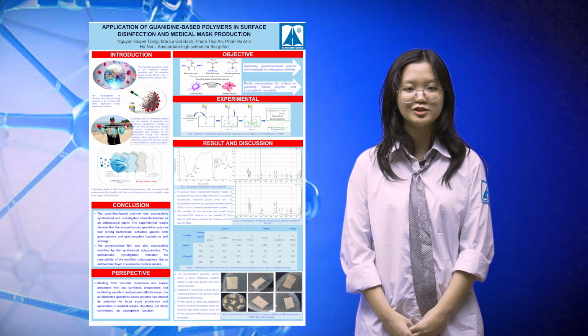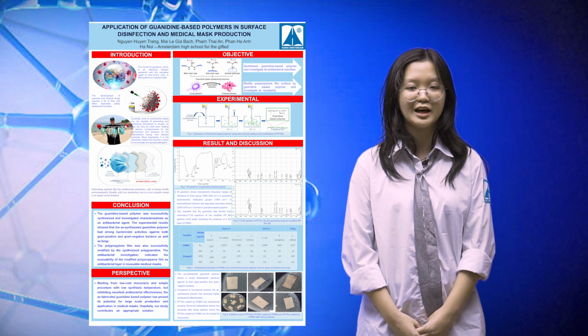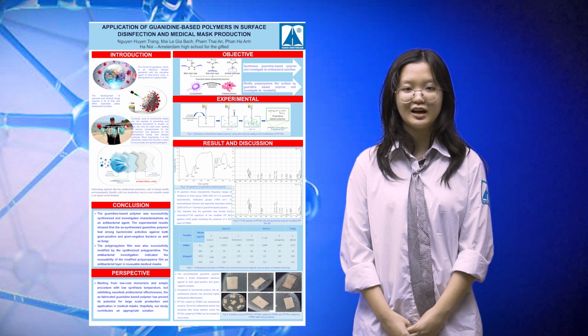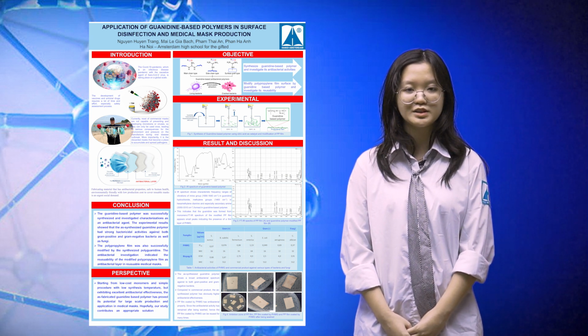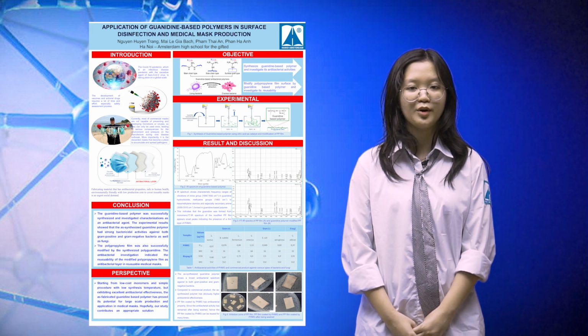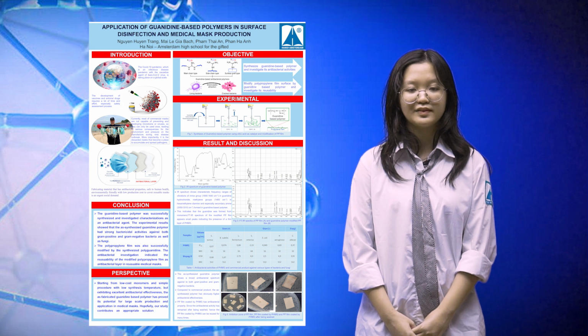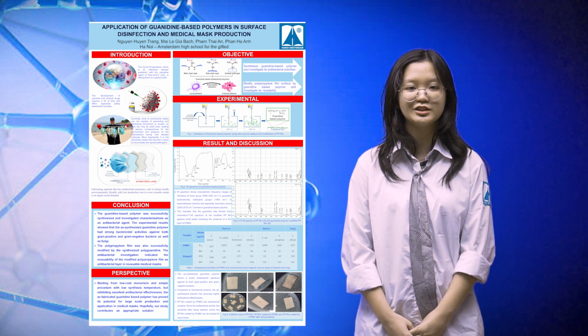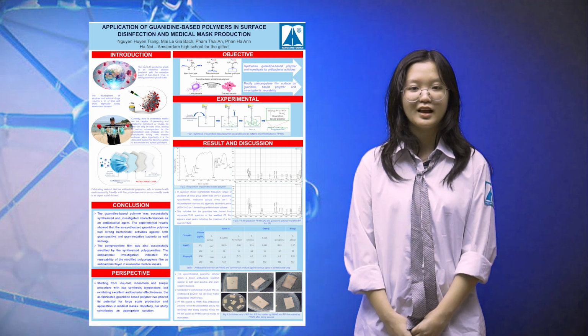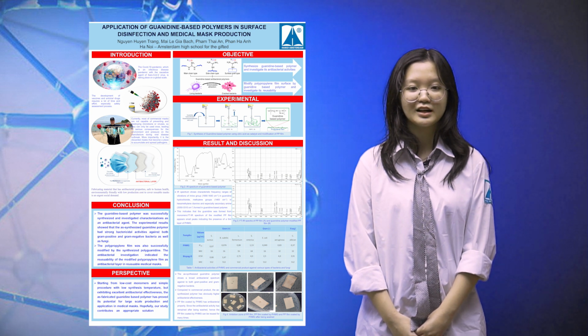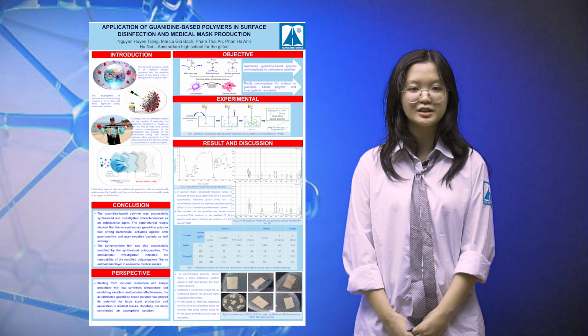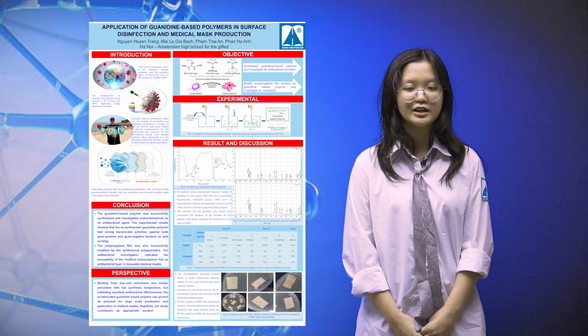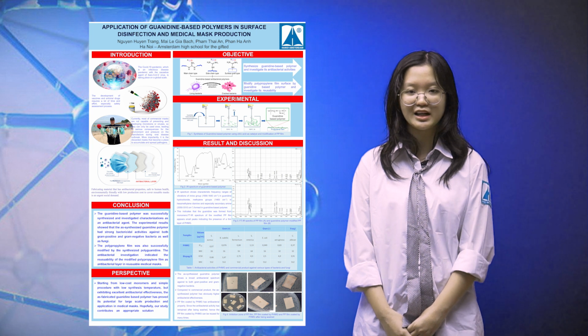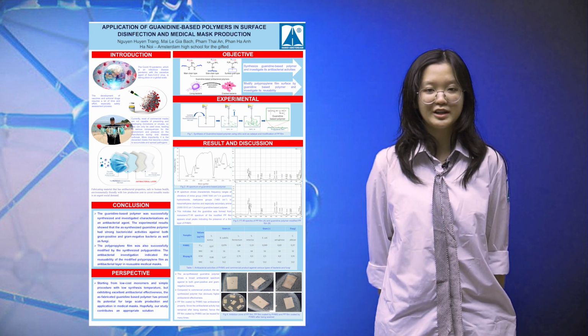First, combine guanidine hydrochloride, hexamethylene diamine, and citric acid in a flask. This mixture is then mechanically stirred at 120 degrees Celsius for approximately 1 hour. During this process, ammonia is released into the atmosphere. Then the temperature is raised to 160 degrees Celsius and the mixture continues to be stirred for another 2 hours. The most remarkable improvement we made in this work compared to previously published studies was to use citric acid as the catalyst, decreasing both time and temperature of the synthesis reactions. In the end, guanidine-based polymer is synthesized.